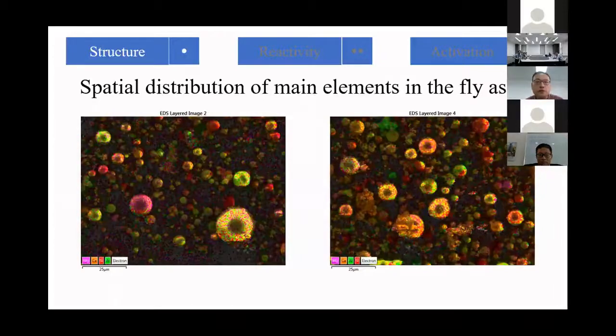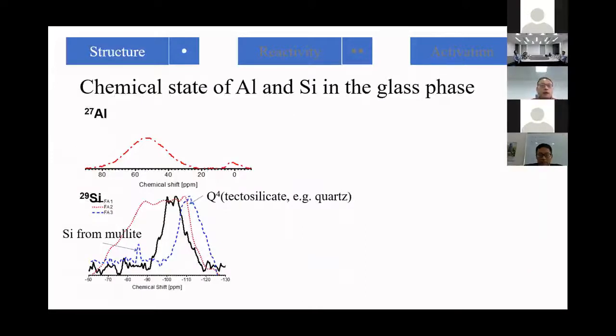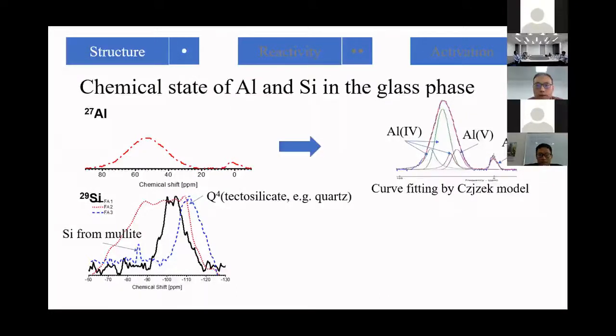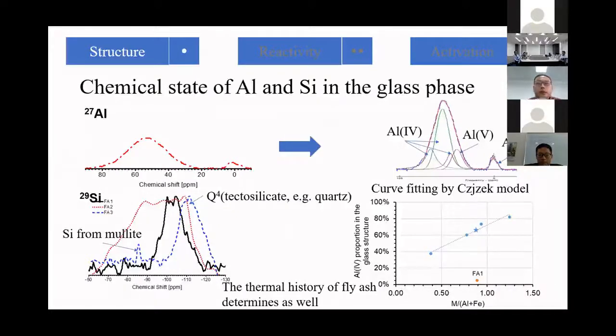For the spatial distribution of these main elements in the fly ashes, it's totally heterogeneous. The chemical elements distributed in these fly ash spheres have no homogeneous structure. It's totally heterogeneous. And from the aluminum and silicon state in the glassy phase, by some curve fitting method using a well-defined model, we can see for the fly ashes, the major aluminum coordination status is tetrahedral coordination, and just a small amount of this fly ash is... sorry, I made some wrong mark.